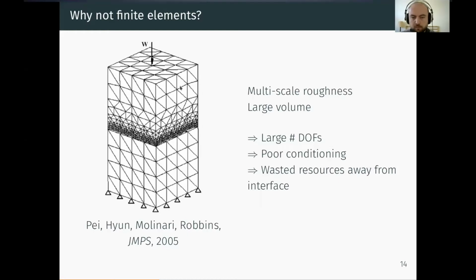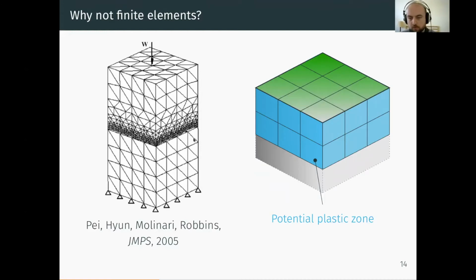You can alleviate some of the computational burden by using a dynamic relaxation scheme, but for plasticity, this may not be an appropriate way to model plasticity because it's path dependent. So there are some issues with finite elements, and ideally we would try to solve those issues by having a numerical method which would allow us to discretize as finely as we can the contact interface, to discretize a part of the volume where we expect to have plastic deformations. And anything else outside of this would be taken care of because it's elastic and we wouldn't need to actually explicitly discretize it.